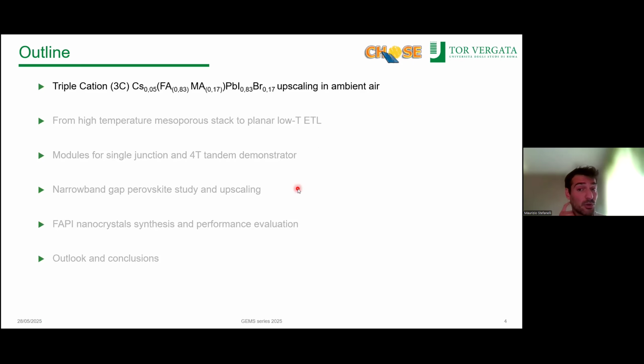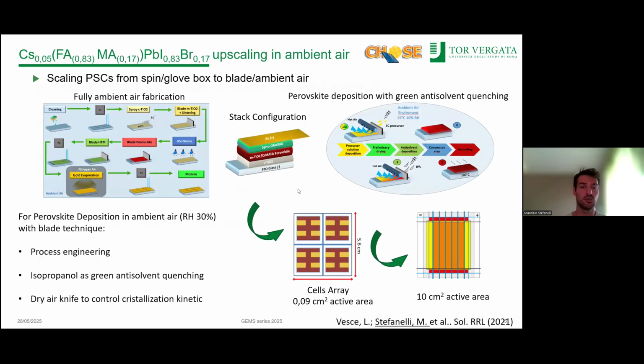So, starting with the triple cation perovskite upscaling in ambient air, I will briefly show you our stack configuration. In this case, this was the mesoscopic NIP structure with compact and mesoporous TiO2, the perovskite, spiro, and the gold electrode. All the processes used to make the device are in ambient air, except for the gold evaporation, of course. We developed and optimized a perovskite deposition that counts 5 steps. Basically, we have the precursor solution deposition with a preliminary drying step with an air knife, and then we deposit our green antisolvent, in this case isopropanol, isopropyl alcohol, coupled again with the air knife to force the crystallization of the perovskite, and the conversion step, and then the annealing.